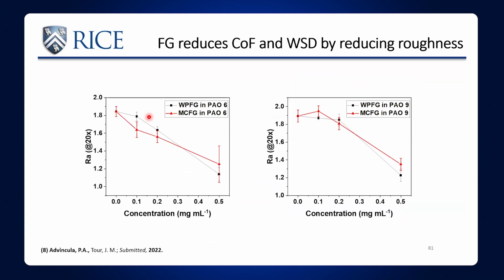And so you can see this reducing in the roughness. And so what you can study is what is the degradation to these steel balls over time. And you do these AFM studies, and you study how those have been deformed. I don't have it in here, but you look at the amount of wear that's taken place, the amount of deformations that you see using these nanometer scale instruments. And you can see the reduction in this, because it's these little nanometer scale increments that you study that end up being big problems over time.